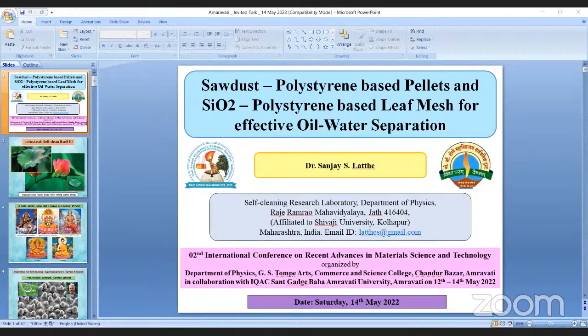As I said while explaining the surface morphology of the lotus leaf, air can be trapped inside the rough structure. So we put the pellets inside the water, and you can see the shiny plastron layer. This shiny plastron layer is because of the air trapped inside the rough structure of the pellets. And when we put some oil in it, the oil gets absorbed inside the pellets, and the air slowly comes out of the pellets. This is just an idea experiment we did.